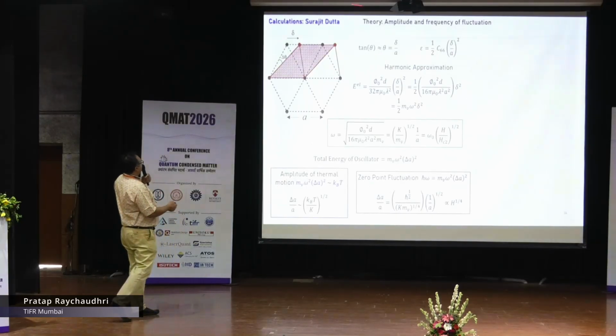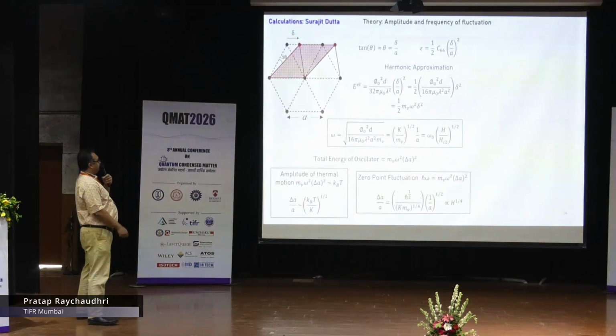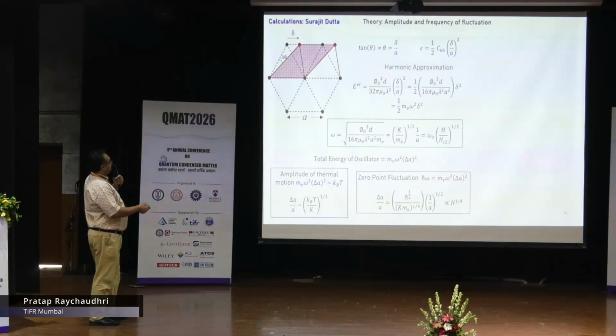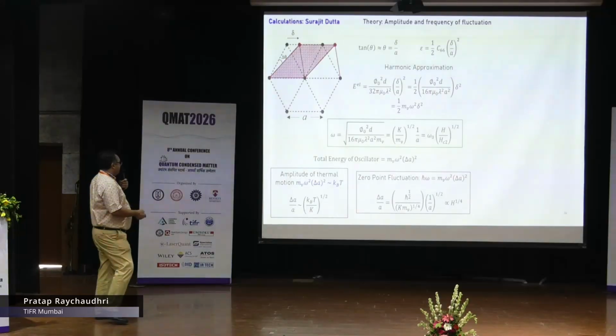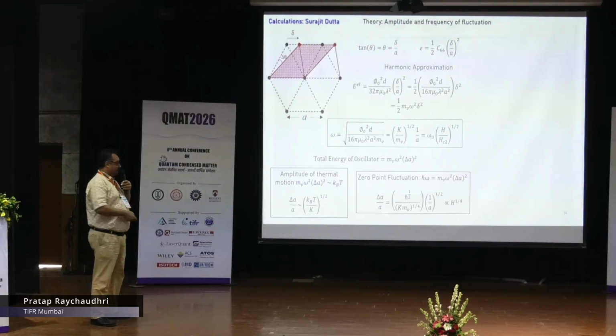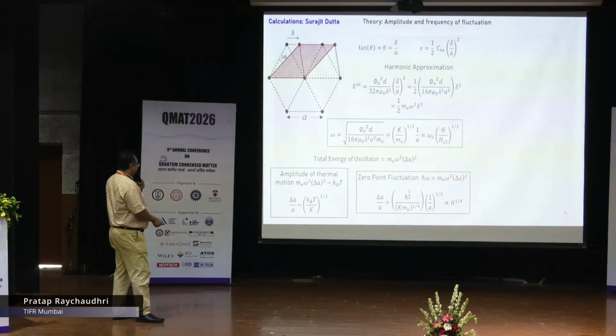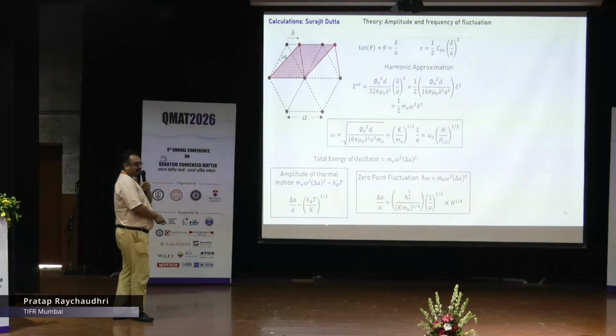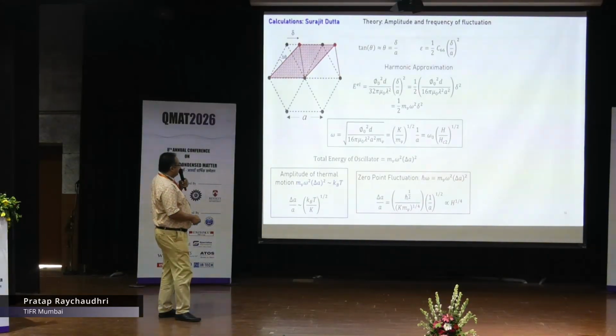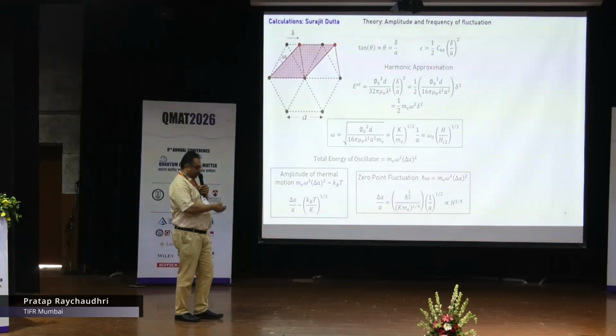For that, Surajit Dutta, the student who was involved in this, did a very interesting and very simple harmonic approximation calculation, from which you can show that if you have thermal fluctuation, then delta A by A should depend on temperature but will be magnetic field independent. On the other hand, if you have zero-point fluctuation, then this delta A by A would be given by this quantity, which means it will go as h to the power 1/4.